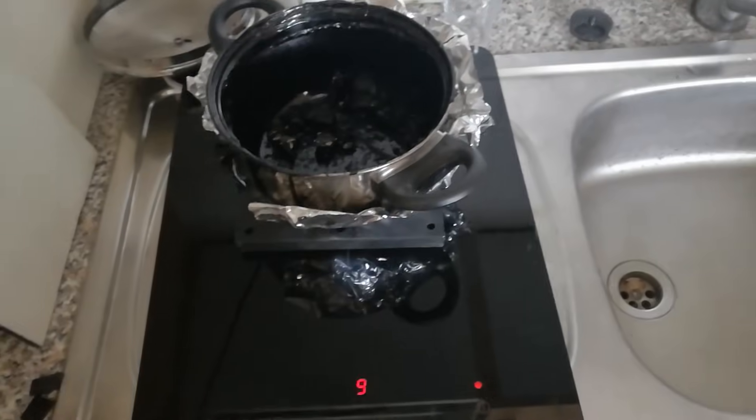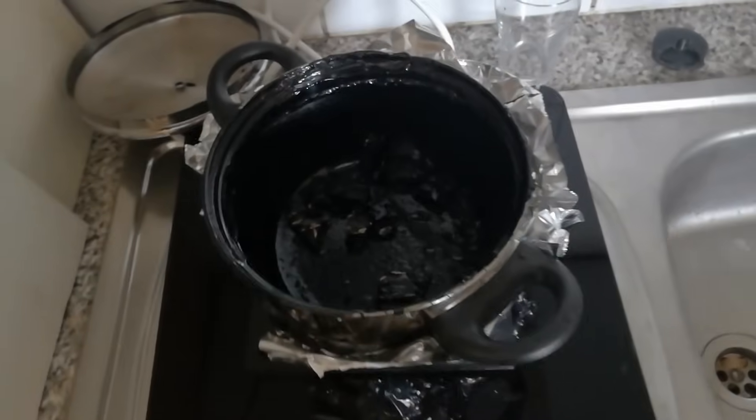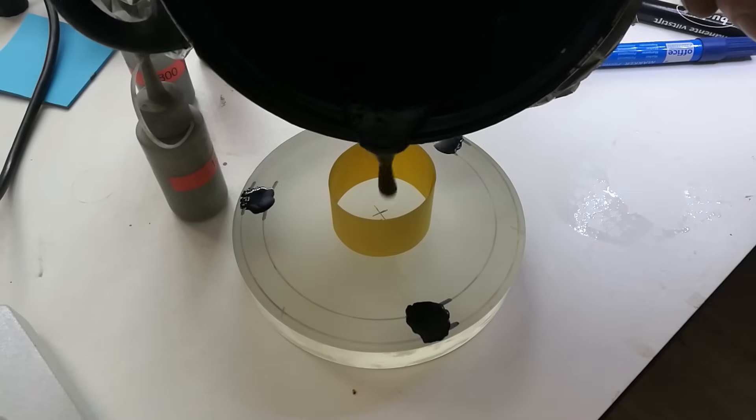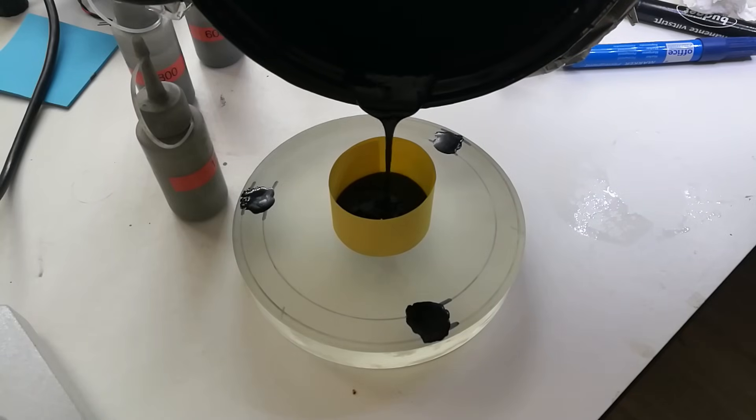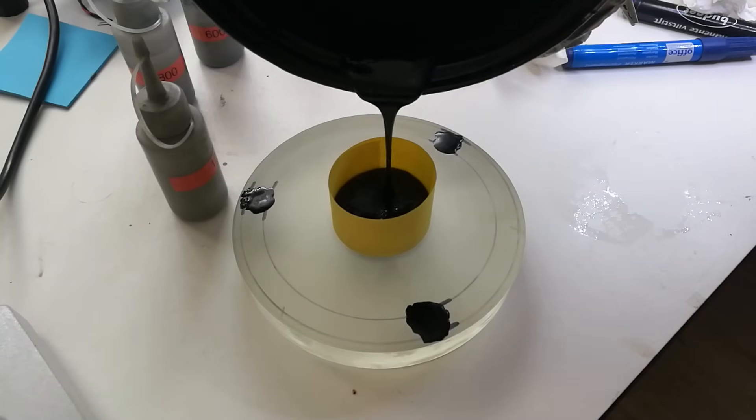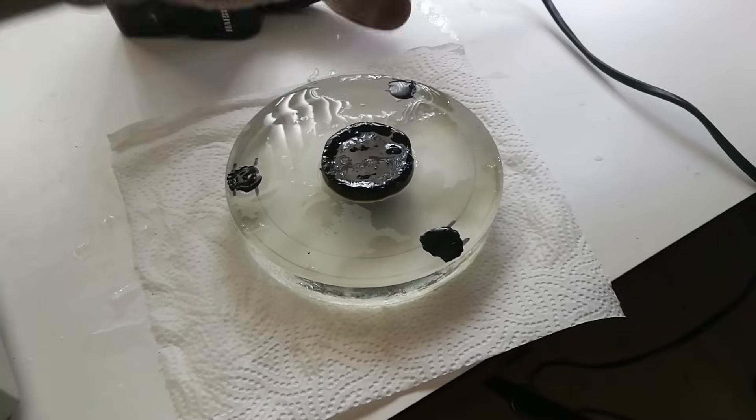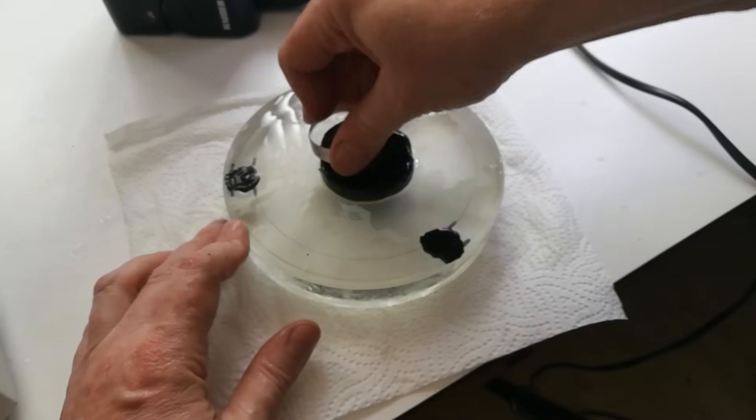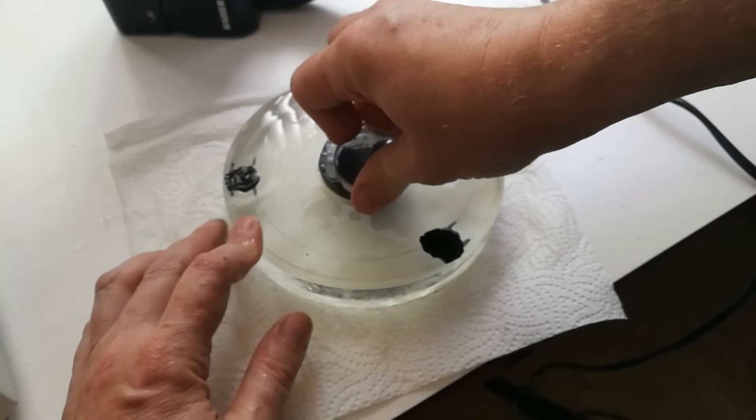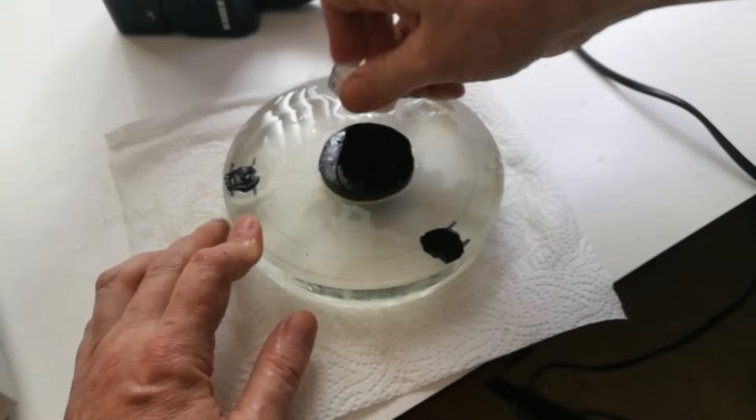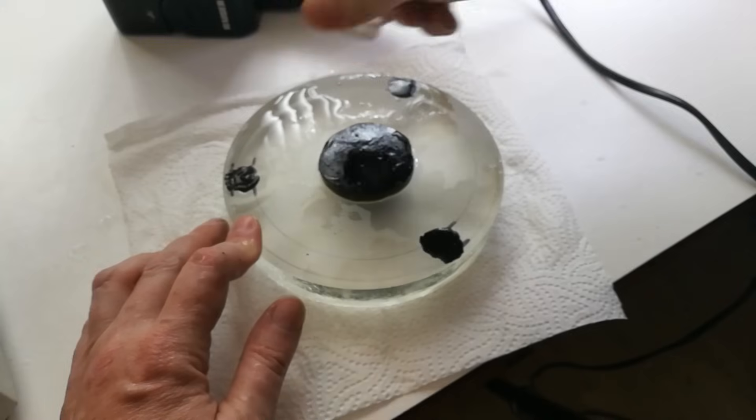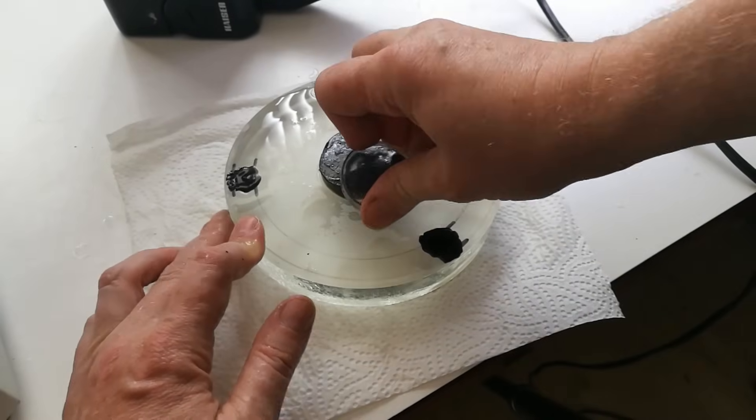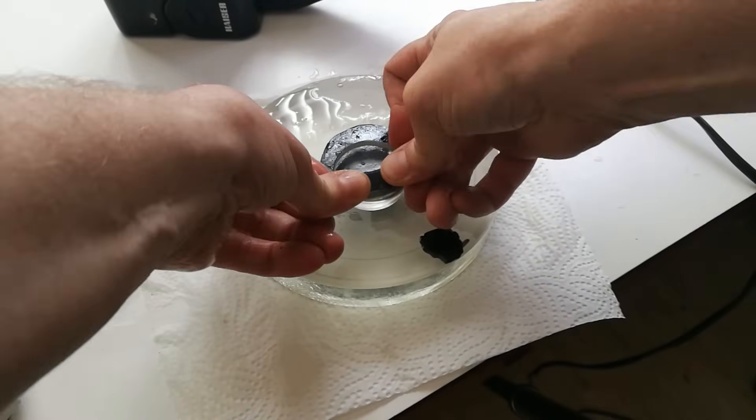To make a pitch tool, the pitch is heated up to about 100 degrees Celsius and then poured on a convex glass chuck. As the pitch cools down, the viscosity goes up again. When still warm, the pitch is pressed in the shape of the blank. In this case we make the pitch tool slightly larger than the blank since this makes it easier to achieve a spherical shape when using the mirror on top configuration.